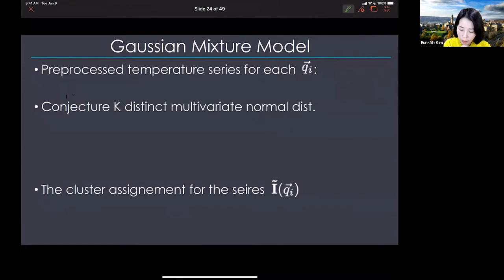To apply our Gaussian mixture model, which we called XTEC, the first step is to pre-process the temperature series for each reciprocal space position, Q of I. So I have a vector, because I measured this at different temperature points. My vector is associated with a particular reciprocal space position. I have different temperature measurements, and I could have measured it for some dt dimension. For some data sets we looked at, sometimes we have 30 temperature measurements, sometimes 20, sometimes 40. And then the next step is to conjecture multiple k distinct multivariate normal distributions.